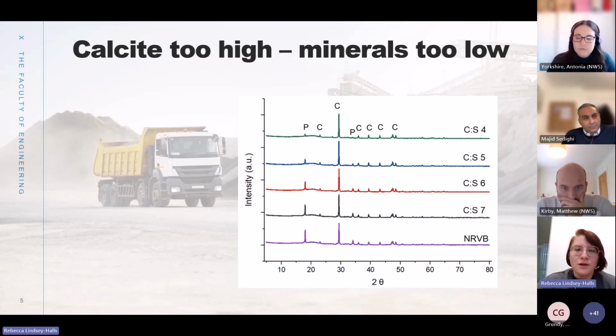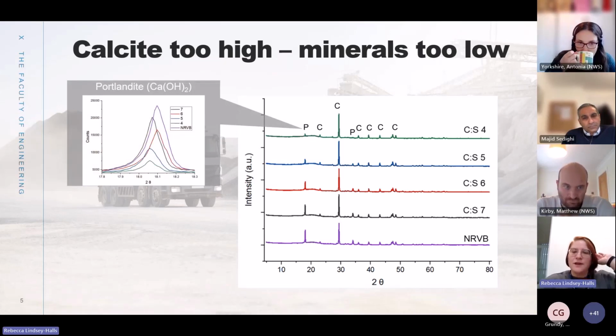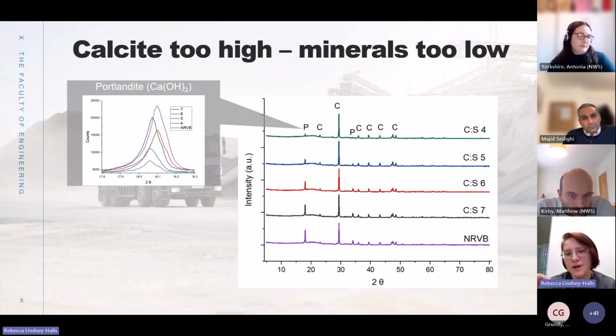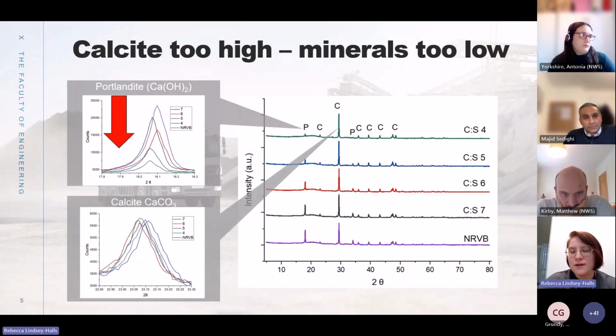As you can see from this, the only minerals that you can really identify are the calcium carbonate, which was put in at the beginning, and also the calcium hydroxide. As you can see from this zoomed in peak, as you add more silicon dioxide, so you're reducing the ratio from 7 to 4, the amount of portlandite decreases. This shows that it is participating in a reaction. However, the amount of calcite remains stable, so it remained constant no matter how much silica you put in or the curing temperature.